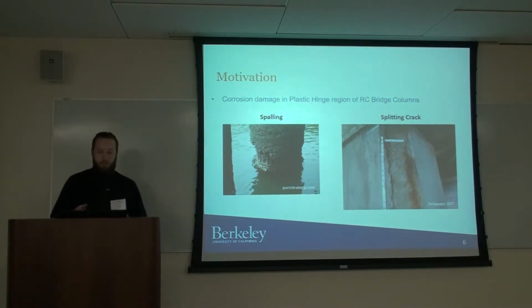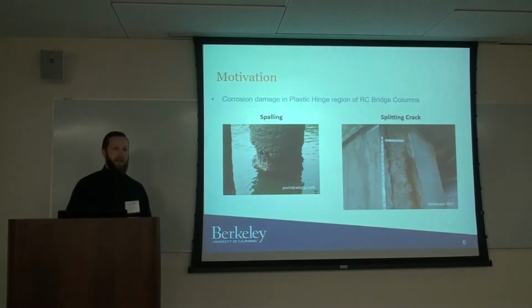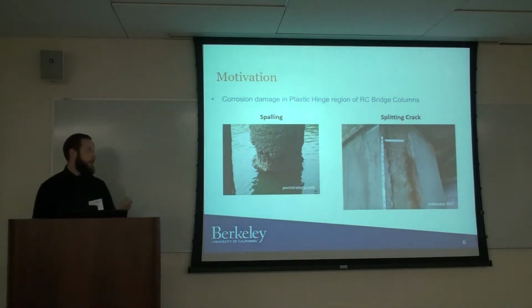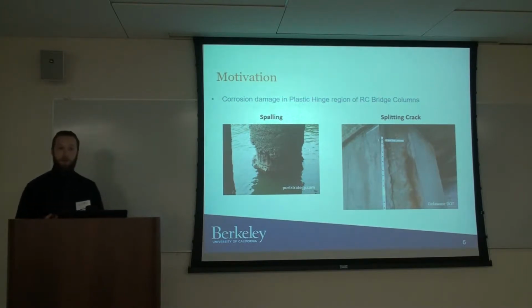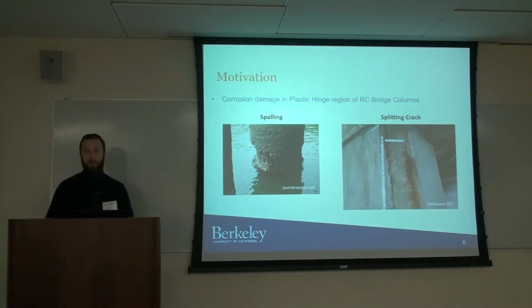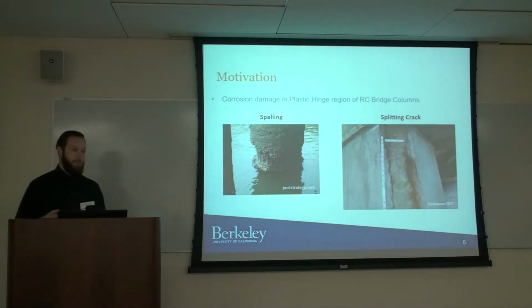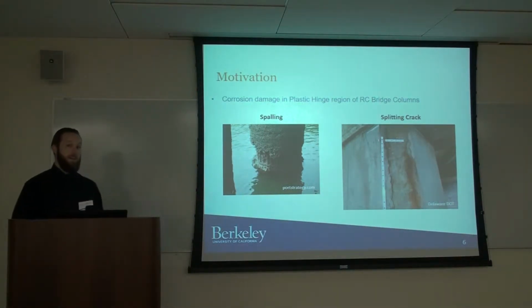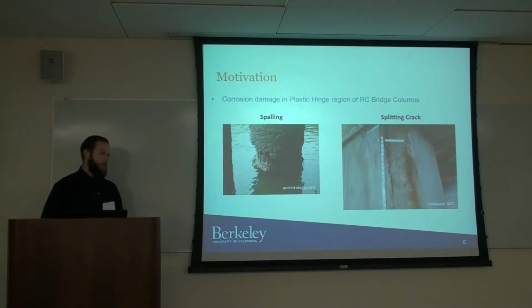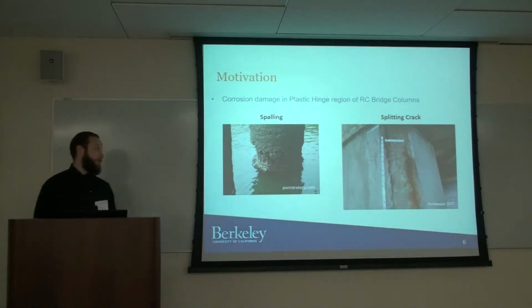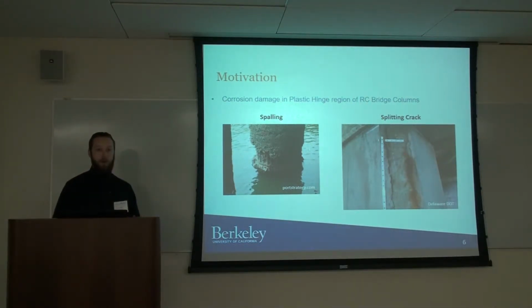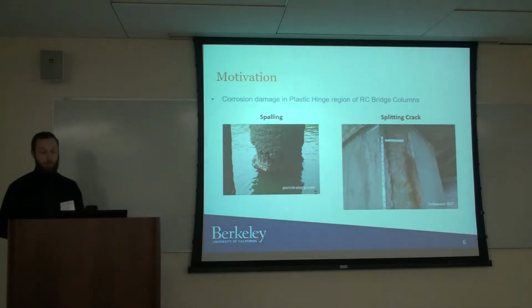And just to give you some examples of damage, here we see some significant spalling, and another, where even before you reach spalling, you can have damage that affects mechanical behavior, especially splitting cracks, which deteriorate the bond between reinforcement and the concrete, and this significantly deteriorates flexural behavior. This is significant because this type of damage can often be found in the plastic hinge region of reinforced concrete bridges, and given how important these regions are to drift of bridge structures, it's important to understand the interactions between corrosion damage and seismic performance.